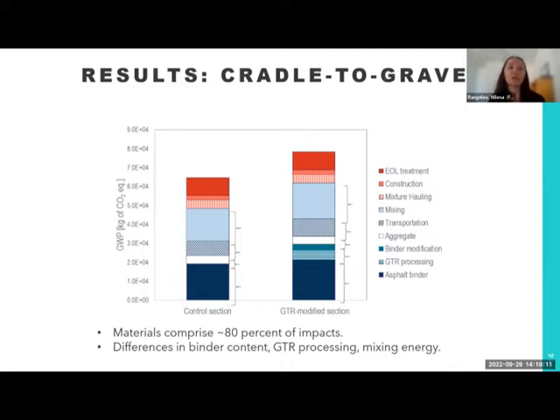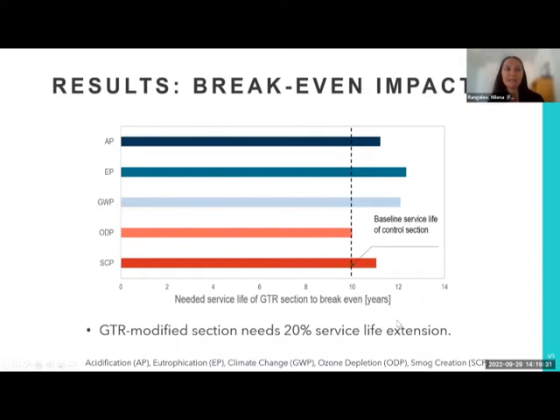Mixing is another important chunk and a little higher for GTR mixes because it requires higher temperature. And then we can see construction and end-of-life treatment, they comprise around 20% of impact, so the bulk of it is materials, is the initial construction. So GTR impacts are higher. However, these impacts can be compensated for if section presents improved performance. So how much better we need GTR section to perform so that it breaks even, quote unquote, with conventional section in terms of environmental impacts.